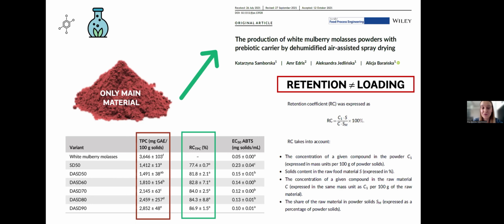As you can see over here in this red frame, this is the total phenolic content of white mulberry molasses powders, and with increasing carrier content down to 10%. And as you can see over here, due to increasing the content of molasses, the total phenolic content increased, but at the same time, when we were calculating the retention coefficient in a new way, we noted that there were no significant differences between the variants.